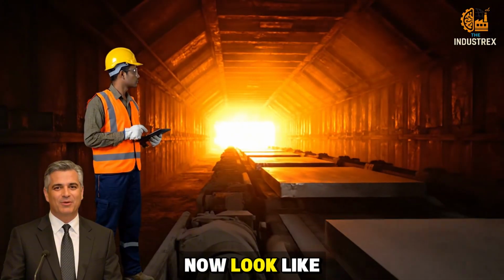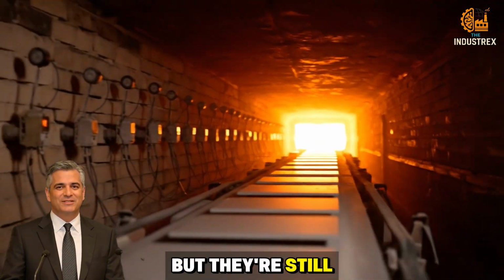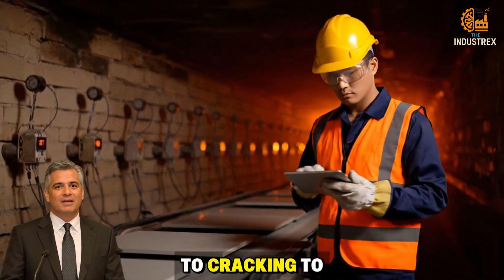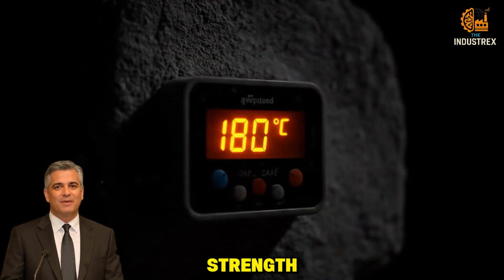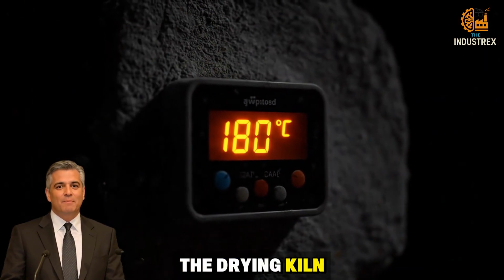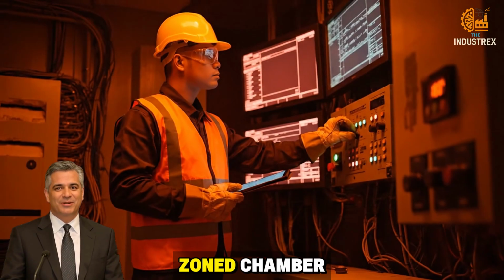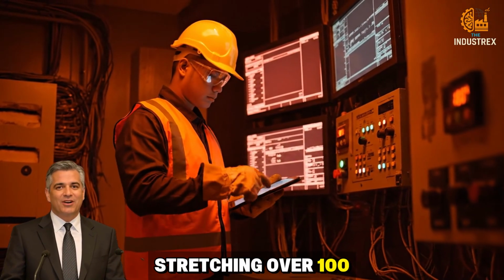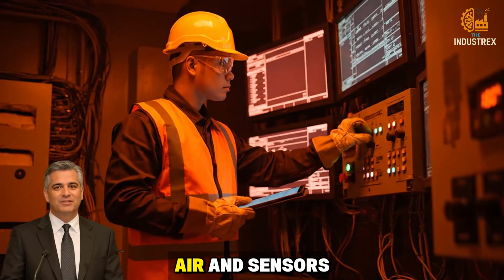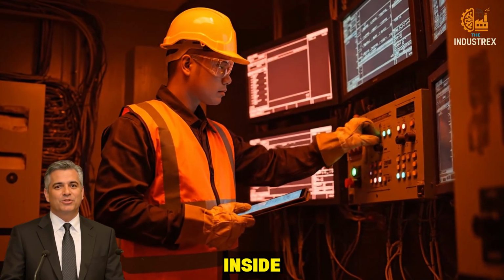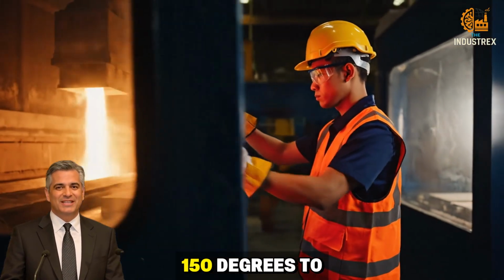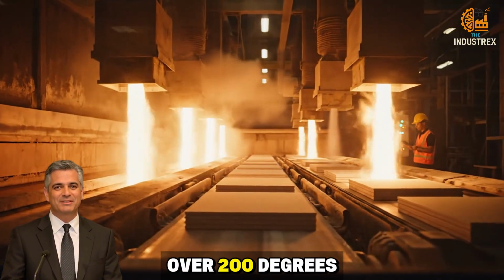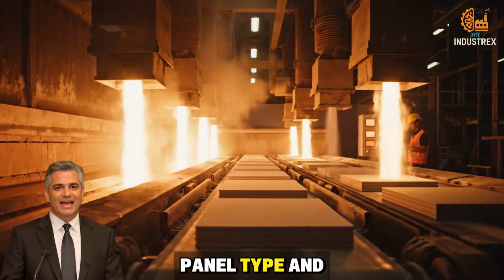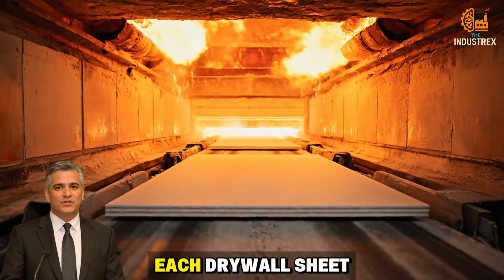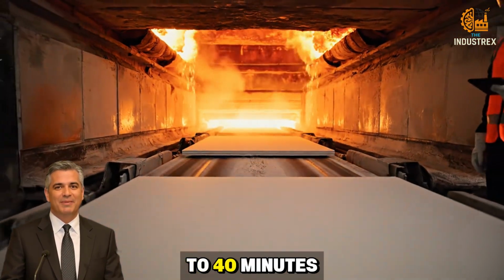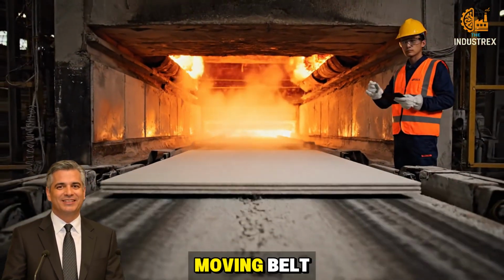The cut panels now look like drywall, but they're still fragile, damp, and prone to cracking. To gain their final strength, they must enter the drying kiln, a massive, multi-zoned chamber stretching over 100 meters long, humming with hot air and sensors. Inside, temperatures range from 150 degrees to over 200 degrees, depending on the panel type and moisture level. Each drywall sheet spends around 30 to 40 minutes passing through the kiln on a moving belt.